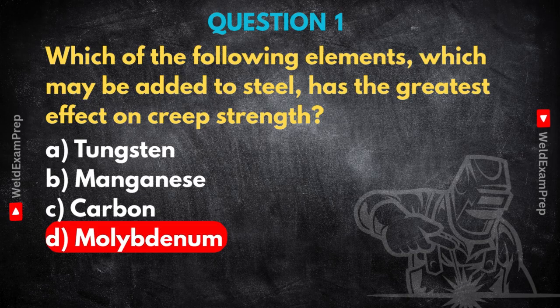Molybdenum. Okay, why? What does it do? It's actually quite fascinating. Molybdenum has this ability to form very stable carbide particles within the steel, especially at high temperatures. Think of these carbides like tiny little anchors spread throughout the steel structure. Yeah, they effectively pin the grain boundaries and make it harder for the internal structure, the dislocations, to move around. And it's that movement that leads to creep. I see. So it locks the structure in place even when it's hot. You got it. It provides that high-temperature structural stability.